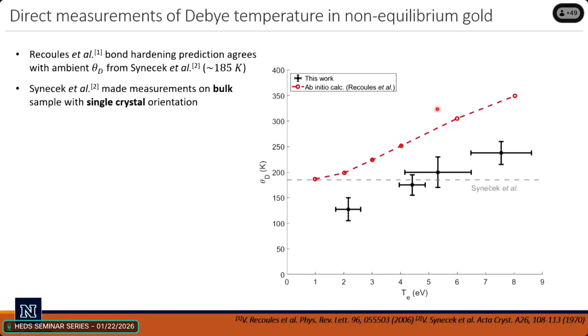And I'll skip ahead and say that we did this. We measured the Debye temperature in these systems for 4 different electron temperatures, and we got these points right here. This is the prediction of the bond strength from the original paper. And you can imagine when I saw this, I said to my graduate student, Travis, you've made a mistake. You've made about an 80 Kelvin mistake somewhere. Go and find it. This is clearly meant to be up here, right? And we could not find a mistake in anything that we did. There are no free parameters. You just plug the ion temperature and the Bragg peak intensity into the equation, and out pops this. There was nowhere to go.